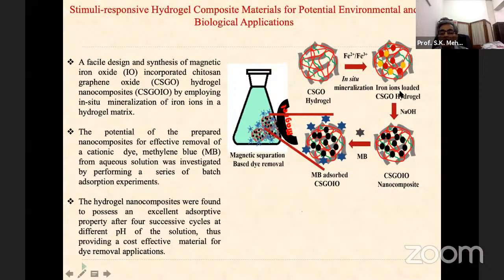This can be created if you use sodium hydroxide for this purpose, and you can create this CSGO IO. IO is nothing but iron oxide nanocomposites. So we used this prepared nanocomposite for the effective removal of a cationic dye, for example methylene blue, for which a lot of work has been done. Removal from aqueous solution was investigated by performing a series of batch adsorption experiments.